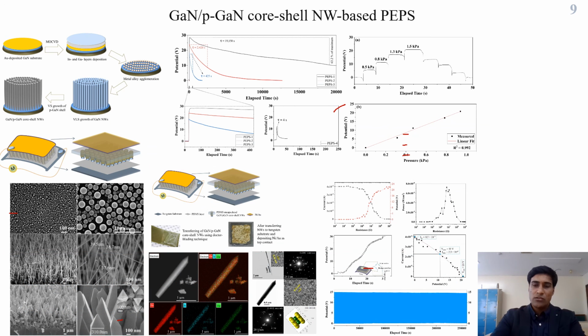Its long-term durability was tested for 3 consecutive days, and we observed only 3% degradation in the output voltage with continuous measurement for 3 days at 1 Hz frequency. So this was about the GaN/p-GaN coaxial nanowire based pressure sensor, in which we suppressed the leakage current, and because of that the voltage decay time constant was enhanced.